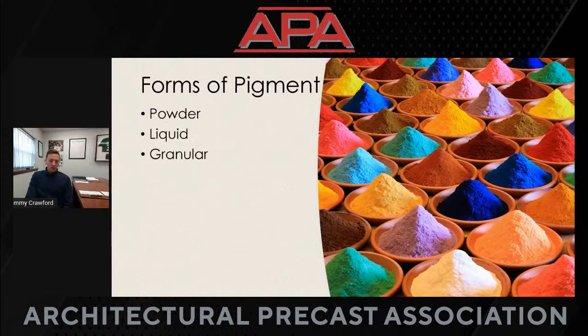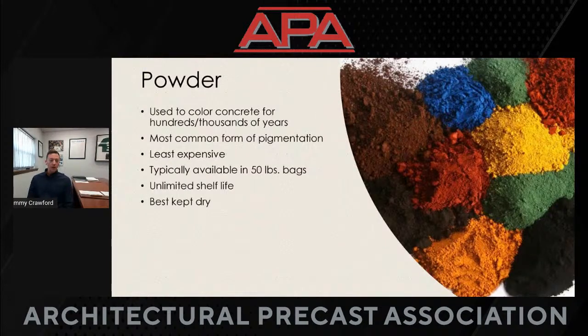Alluded to this a little bit earlier, but there are 3 different forms that iron oxide pigments are available in. Powder, which is the most common. Liquid, which is a suspended solid product where you're basically suspending pigment in water and some other chemicals. And then granular, which is little BBs that are the pigments encapsulated by a binder. And we'll get into why you would look at each of those options in the next slide.